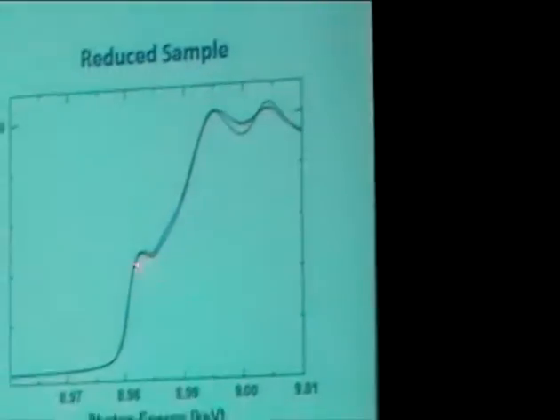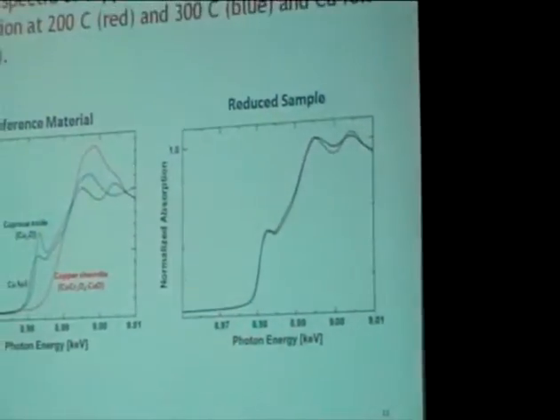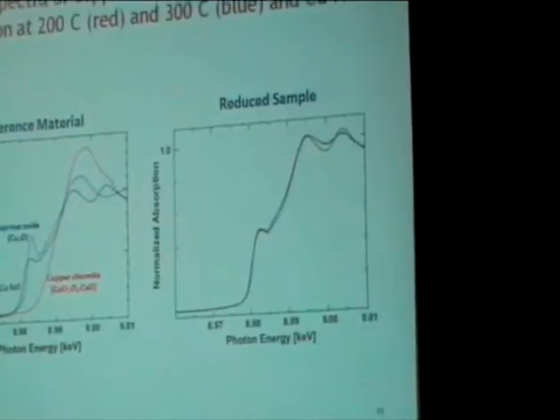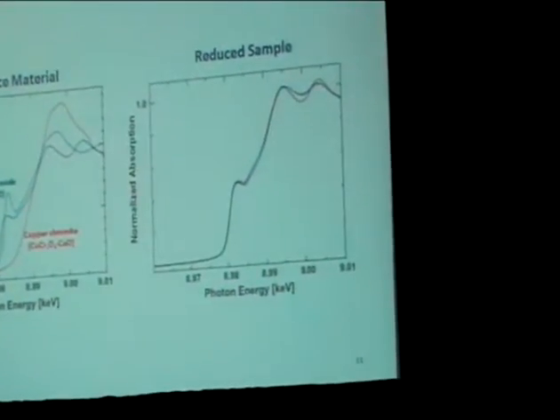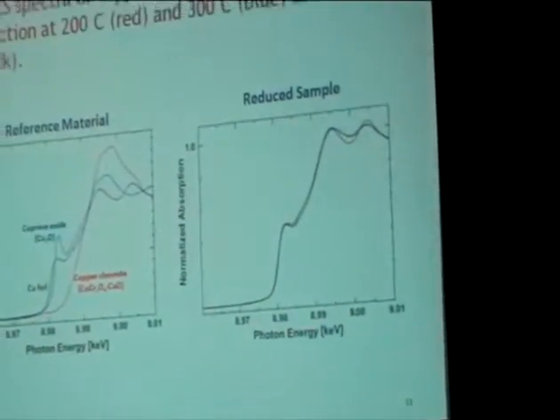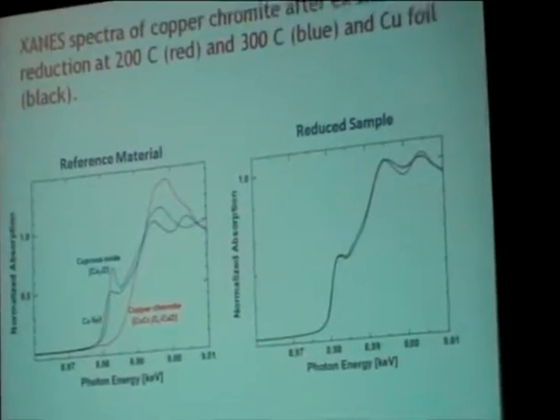On the right-hand side, if you're close enough to the screen, you can probably see that there are actually 3 curves here, okay? Maybe even in the back. But basically, when we reduce this sample, everything goes to reduced metal, and this lines up directly on top of the XANES for the copper foil. So the active component here is a copper 0 component, not copper 1+ that has been pushed heavily by the open literature there.